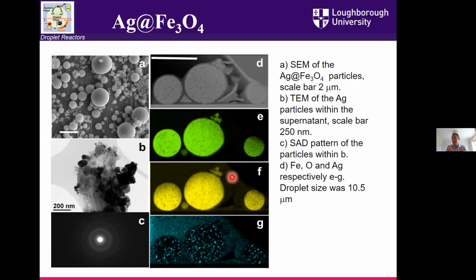They're solid iron oxide. These are all clusters of nanomaterials. We're not seeing the resolution of the nanomaterials there, but they're all drawn together after the hexane and solvent has been evaporated. And the bottom picture here shows us where the silver is. And so the silver isn't on the outside as I expected it. It's in the liquid because it's been shed from the droplet, but it's also been encapsulated within the droplet.